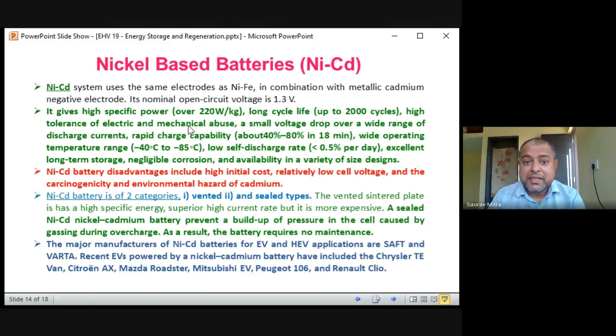So a nickel cadmium battery can withstand electrical and mechanical abuse to a greater extent. It has a small voltage drop over a wide range of discharge current, and rapid discharge capability. Almost 40 to 80% can be discharged in only 18 minutes. That means it can give a high discharge rate of current. It has a wide operating temperature range, minus 40 to 85 degrees, which it can withstand.